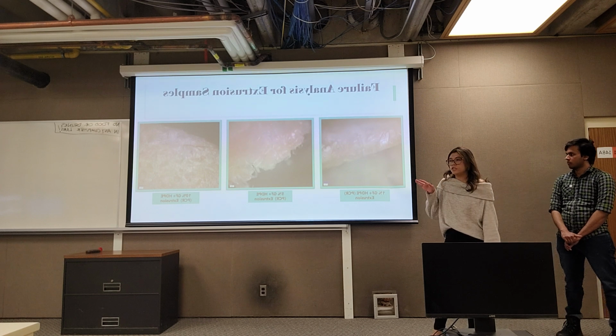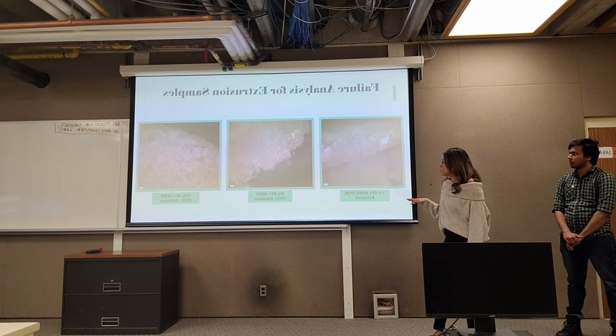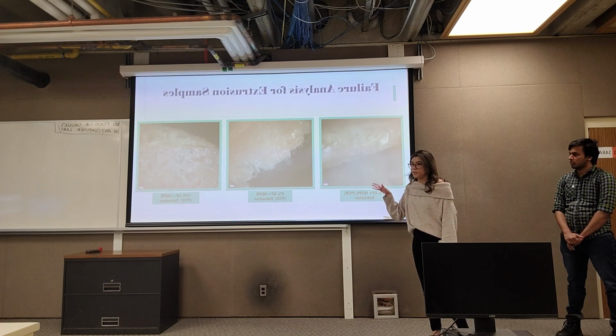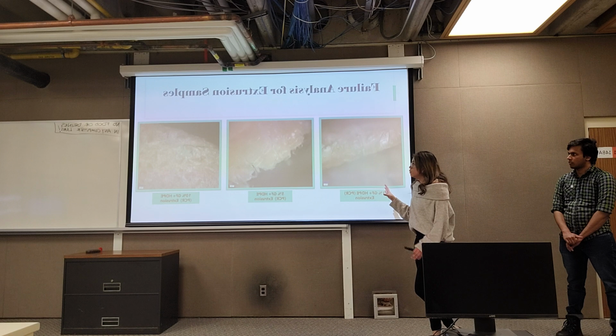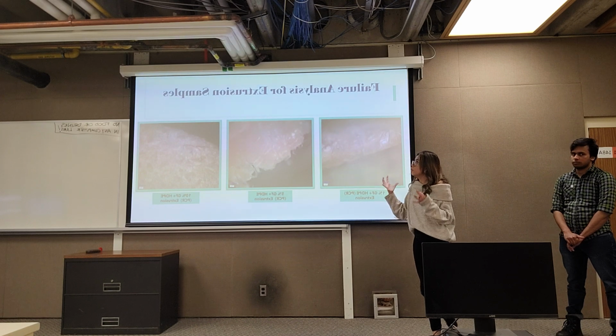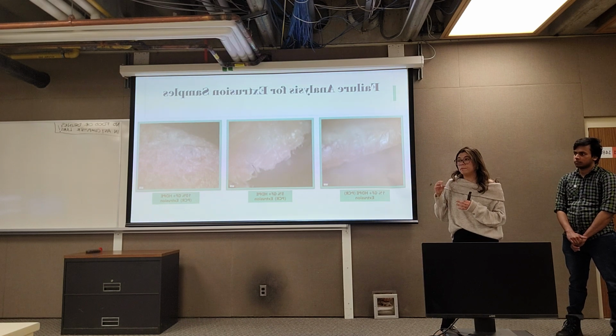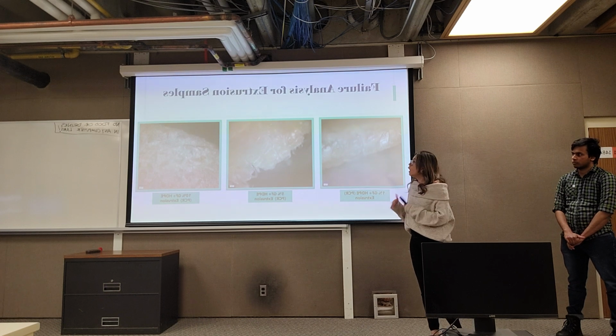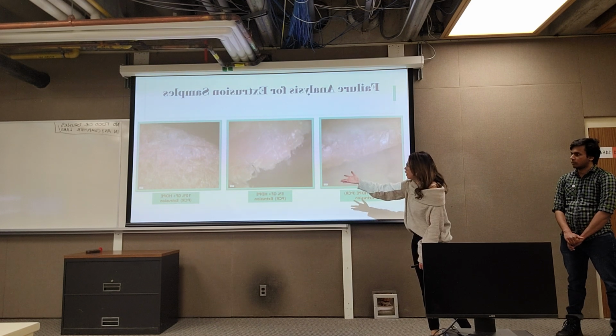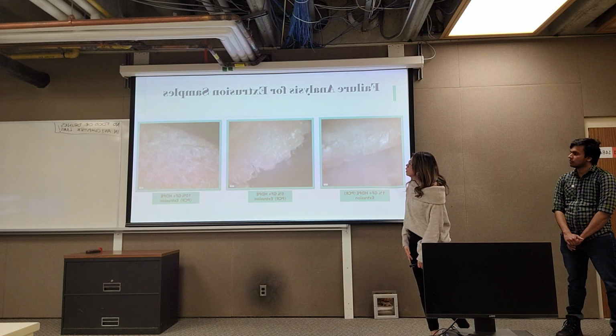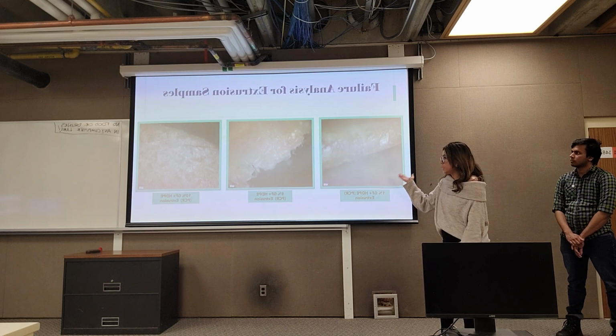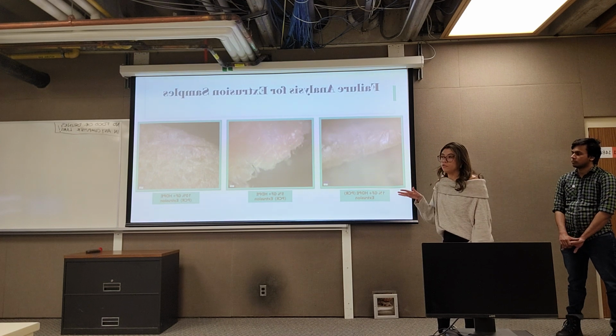We also made three other sets of samples using compounding extrusion with different percentages of reinforcement. Here we observe that we improve the mixing of the fibers and the matrix compared with the molding process, as well as improve the binding of fibers and matrix. And we didn't observe fiber pull-out in the failure analysis. Instead, we had some jagged edges in the surface, which can indicate that we have a brittle failure.